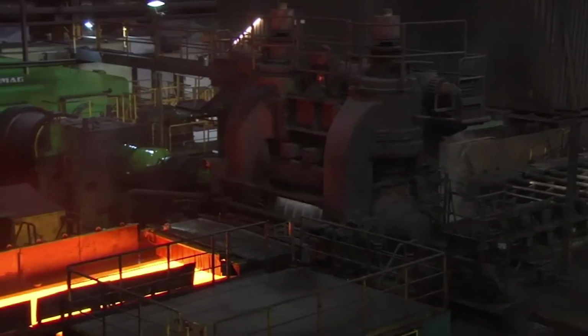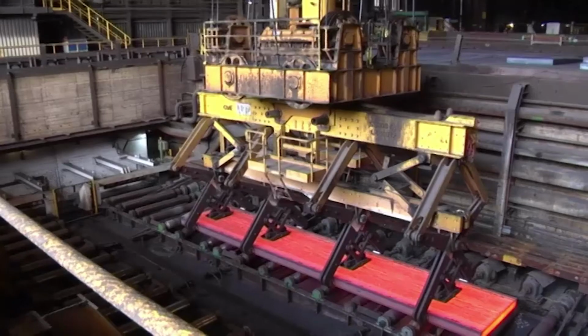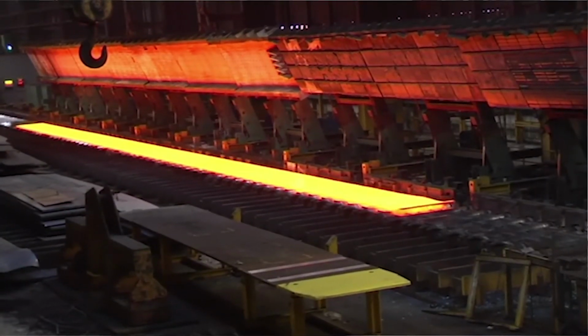And here the main role of niobium comes to light, because it is known that niobium delays the softening kinetics of the steel, and niobium also influences the grain mobility of austenite. And this is done by means of a solute drag effect and by strain-induced precipitation of niobium carbides. So in concept with high niobium and low carbon, it is possible to do the process in high temperature window, and exactly this represents the relaxation of temperature constraint in our finishing train, and also allows us to obtain the desirable microstructure, that is fine-grained microstructure.